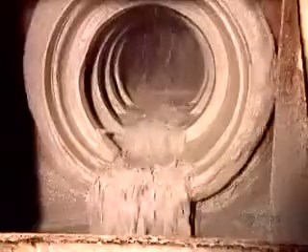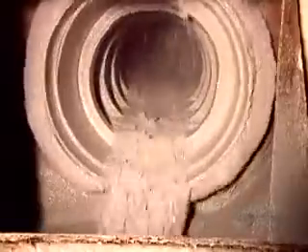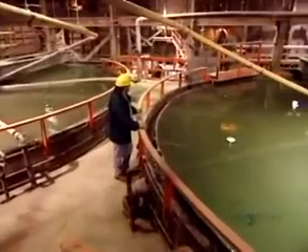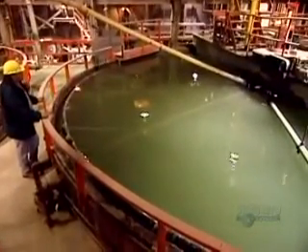The factory adds a water and cyanide solution, then another mill grinds it further into a mud-like pulp. The pulp flows into large settling tanks. The wet solids, being heavier, sink to the bottom. The water at the top drains to another area. They transfer the wet solids to an agitation tank and blow in air.